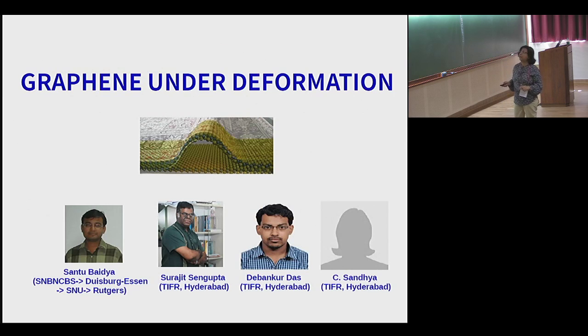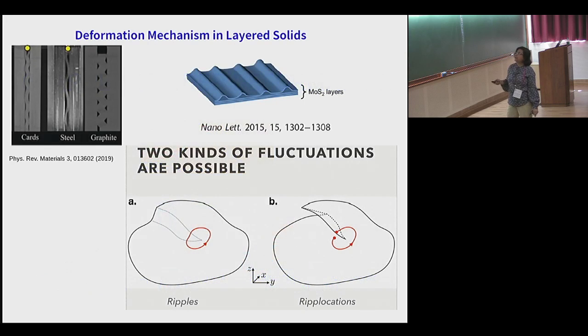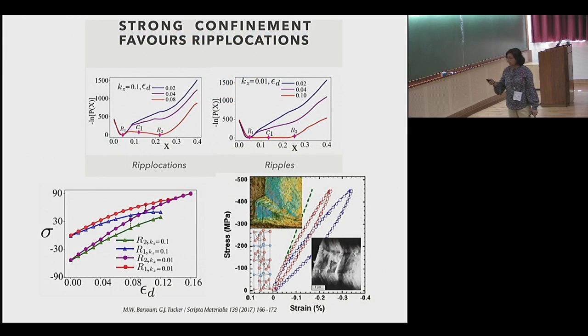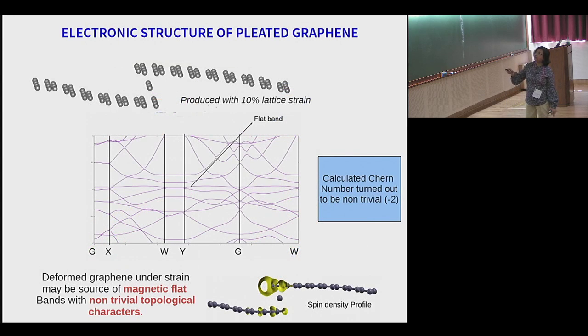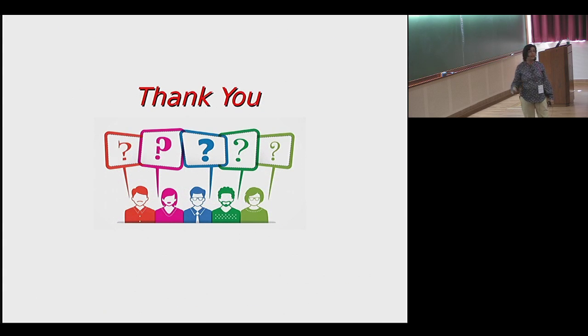The last one, just one comment. This is graphene under deformation. These layered solids like graphene or graphite basically deform by forming ripple-like structures, or ripplocations. The ripplocations are like a pleated structure, and there is a signature in the nonlinearity of the elastic property. I will not get into that, but if you can manage to generate such a pleated structure, its corresponding electronic structure shows the existence of such a flat band together with magnetism, and the calculated Chern number shows a highly non-trivial value for such a flat band. So graphene under deformation can also be a possible host for such flat band topology. With that, I would like to thank you for your attention, and I'll be happy to take any questions. Thank you.